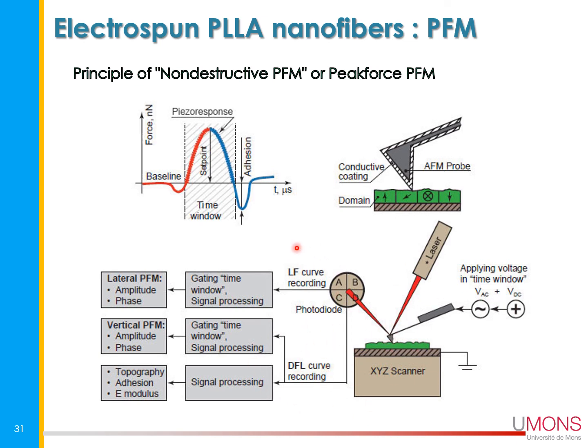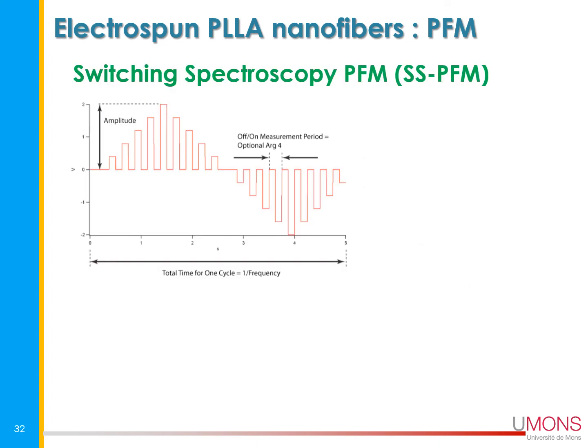from the deflection curve or the lateral force curve, you can get the vertical and lateral PFM as before. And on top of that, in the same experiment, because you are doing peak force QNM, you can have the topography, the adhesion, and also the E modulus. And during this time, you can use the switching spectroscopy. So we have this shape of signal, and we are measuring, of course, when you are reading and not writing.